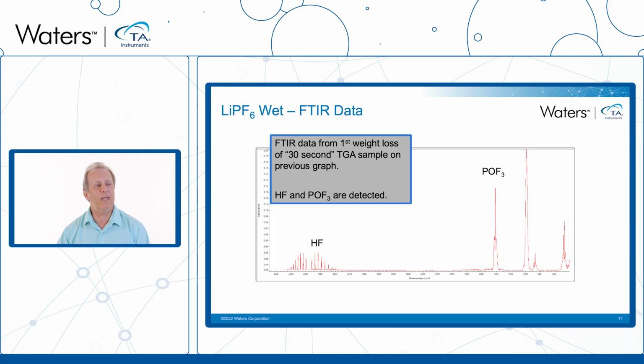Now, again, if we take a look at the FTIR spectrum, and this would be from the 30-second material, we see, during that first weight loss event, now we see HF, and now we see POF3 captured in the FTIR signal. Again, confirming that yes, LiPF6, when it is exposed to water vapor, will produce these 2 components. So this actually shows that the TGA Smart Seal pans are great to use for studying battery materials or other atmospheric sensitive materials.